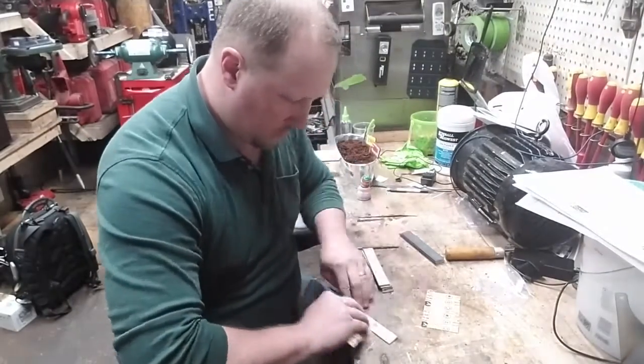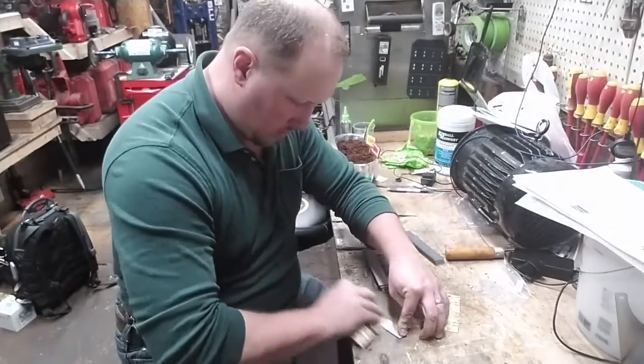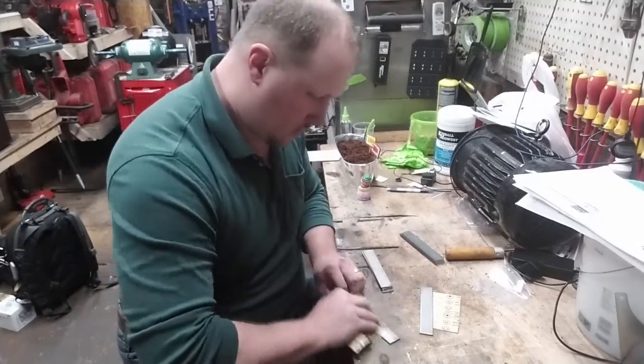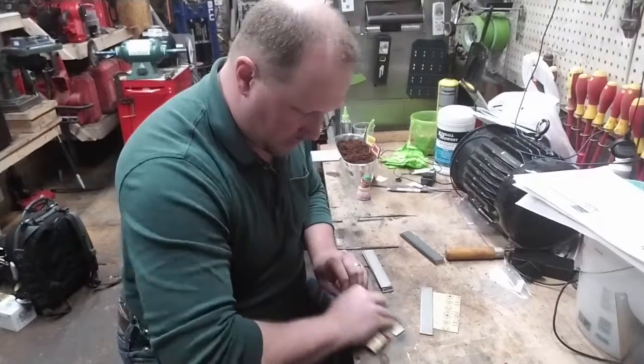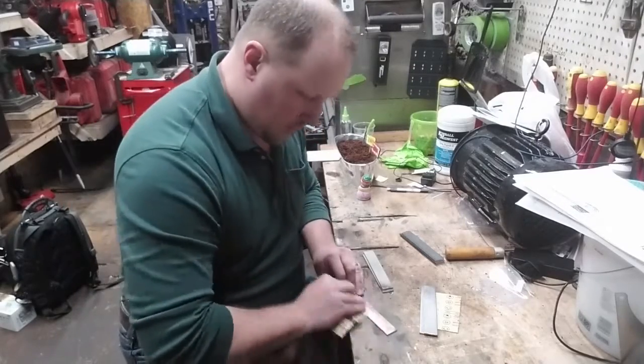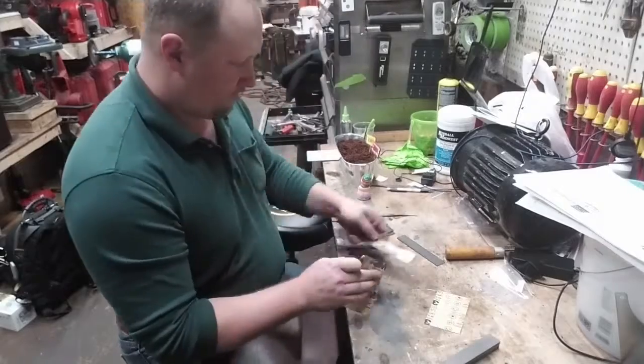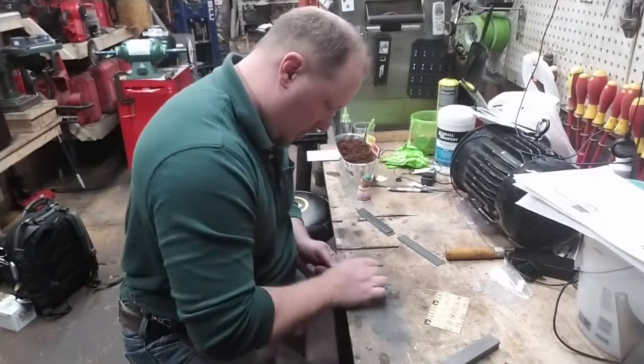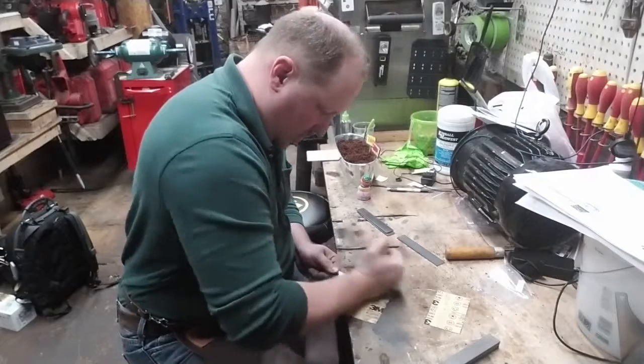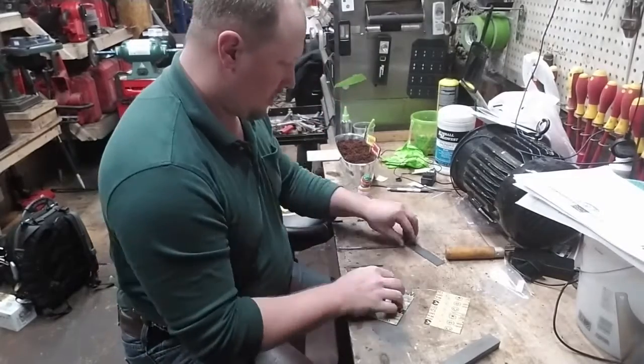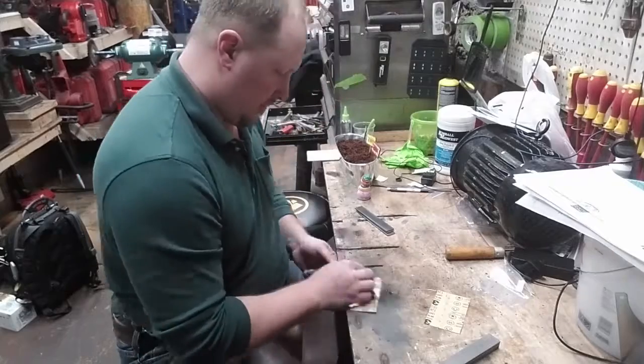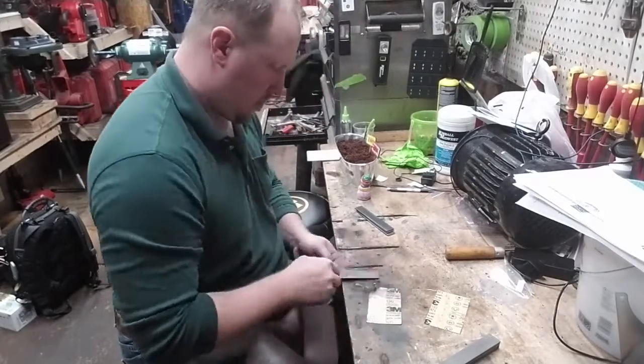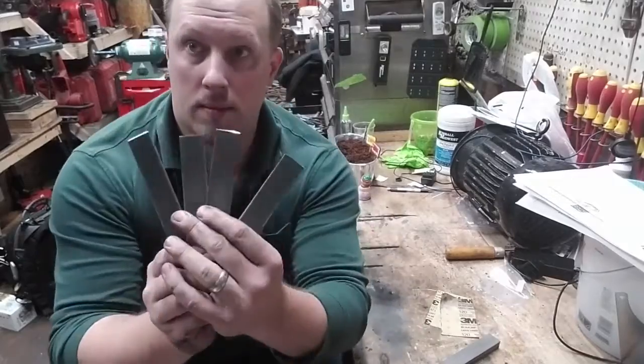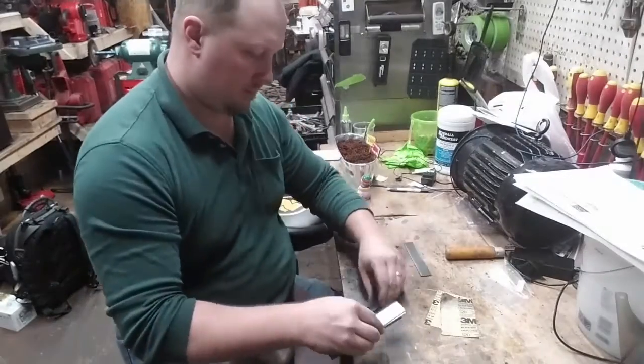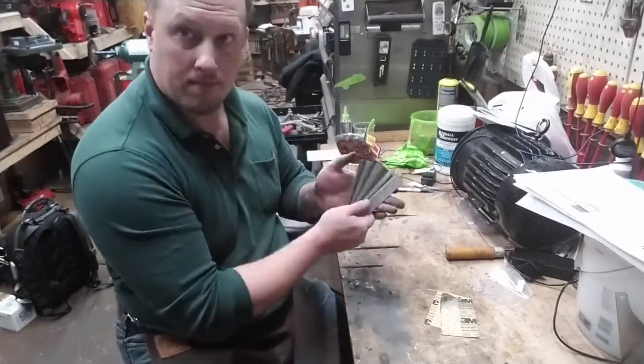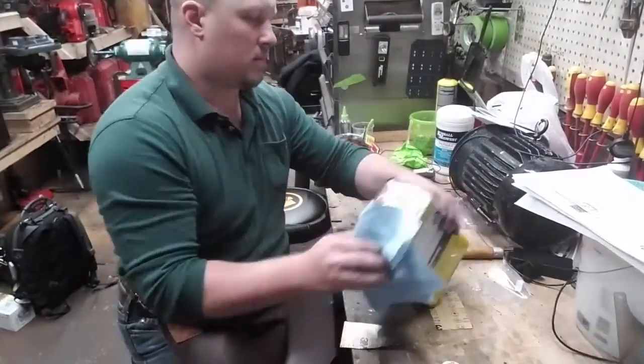The first thing we have to do is material prep, in this case, surface prep. The steel has been sitting for about a week. We've got to make sure that it's bright and spotless so that our weld can be free from any potential contaminants. Even the untreated mild steel has to be sanded the same way. There we have the color difference. I think that's a nice little bit of contrast.